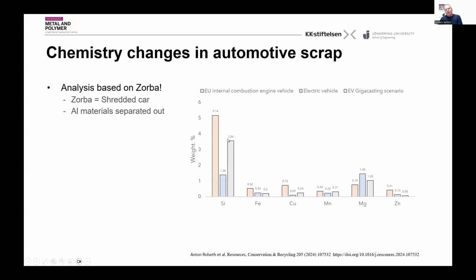And you can see the iron content goes down a little bit because it still used the primary materials for that. And the copper content is a little bit higher compared to what you get from the electric vehicles, but it's still less than what you get from the combustion engines. The manganese content is still in the order of 0.3%. Magnesium is increasing a little bit, and then zinc is even lower here. And this is also because zinc is often coming in from the heat exchangers, and that is something which is going to have a separate scrap route because of the freons and such. So if you take the next slide,